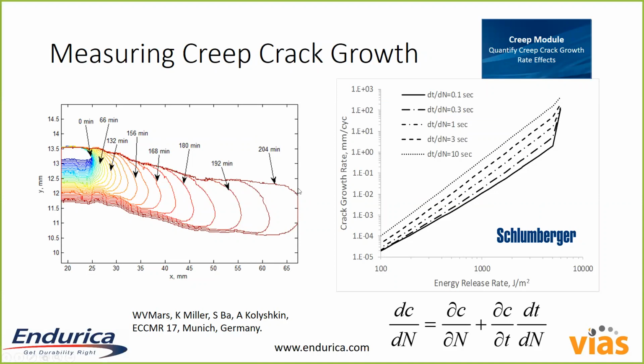So what you're looking at on the left-hand side are actually images of a crack that were taken. This was, I believe, for an HNBR compound, but these are images of a crack that's just being held statically open, and due to creep crack growth over time, you can see I've marked out the time scale here. You can see the crack growing as a function of time. We can take this information and reduce it to what I call a creep crack growth rate curve.